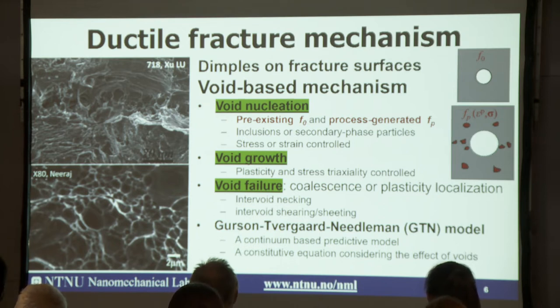We have a very good description of the ductile fracture mechanism. Ductile fracture usually consists of three stages. We have void nucleation. That means we could have initial voids or pre-existing voids, f0. That could come from manufacturing. That could come from the fracture or decohesion of the inclusions with the matrix, from secondary phase particles, from carbides, from grain junctions, etc. The nucleation could be stress or strain controlled. So the process of nucleated voids, I call it fN. In many cases, you can use fN.